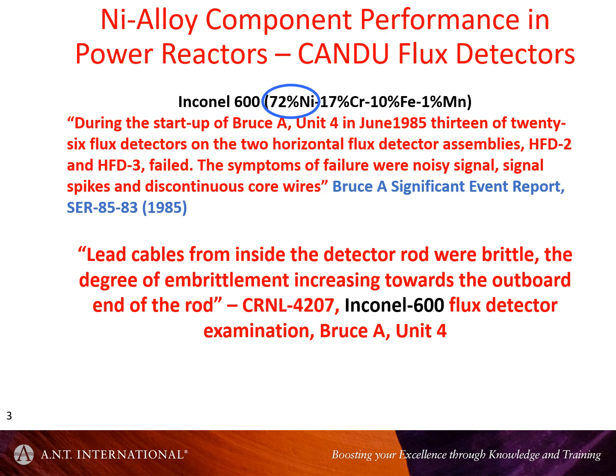So nickel alloys are particularly prone to helium embrittlement because they contain nickel. And nickel in a highly thermalized reactor will produce a lot of nickel 59 from the most abundant isotope, which is nickel 58. And nickel 59 is a very unusual isotope in that it has very high cross-section for helium production, as well as protons and hydrogen production as well, and then gamma reactions. So on all counts, getting nickel 59 produced is not good. Fortunately, it kind of saturates at around about 3% of the total, depending on the burn-in and the burn-out rate and what the spectrum is.